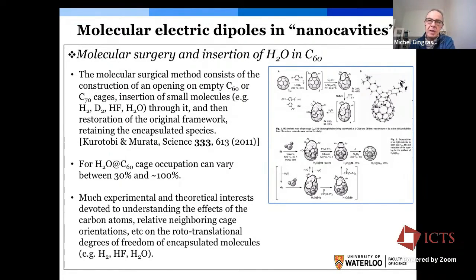And in the case of hydrogen and deuterium, the interactions between the molecules and those in the vicinity, the other encapsulated molecules, are very weak because these interactions would be electric quadrupolar and so extremely small. But the ability to encapsulate dipoles such as hydrogen fluoride and water opens the route to explore the collective physics of dipole interactions for these systems.